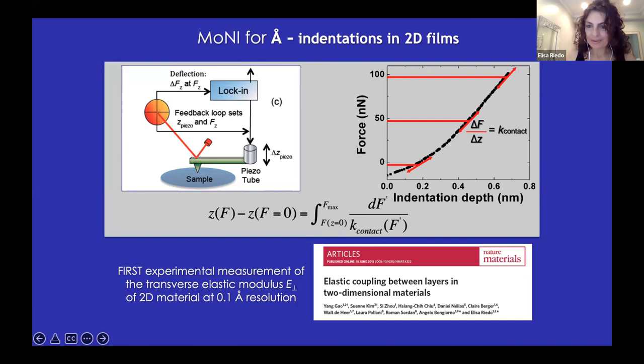Okay, so we arrived here. So this is the modulated nanoindentation method that I was describing before, where we use a lock-in to apply a very tiny modulation onto the piezo tube, and then we detect the change in force. And essentially, for every load, we measure delta F over delta Z. And then by integrating, we really increase quite a lot the signal-to-noise ratio.